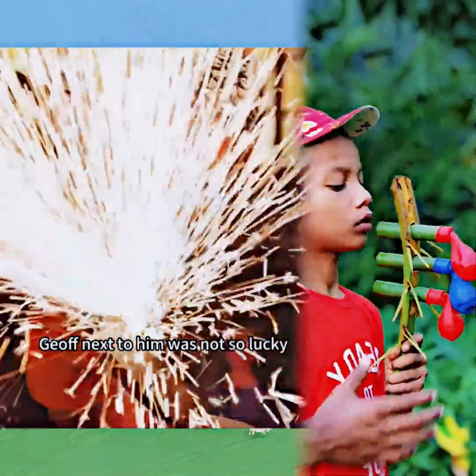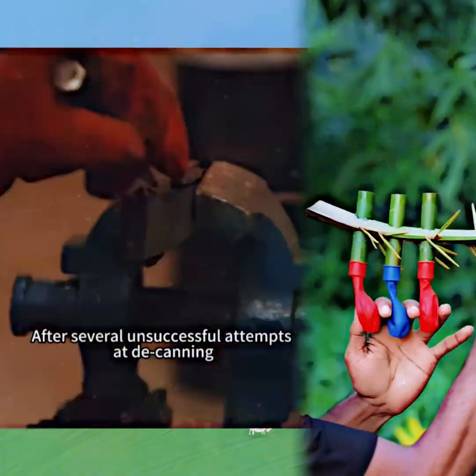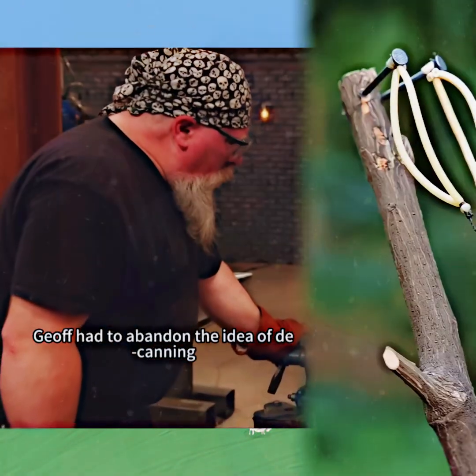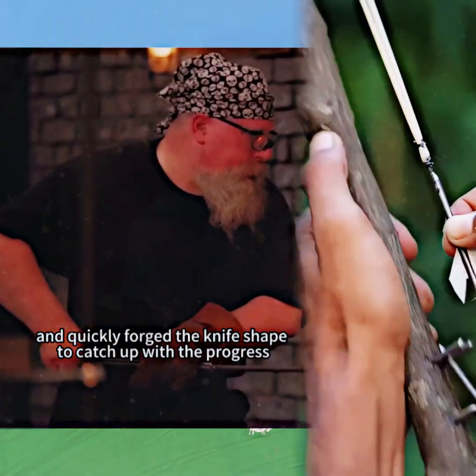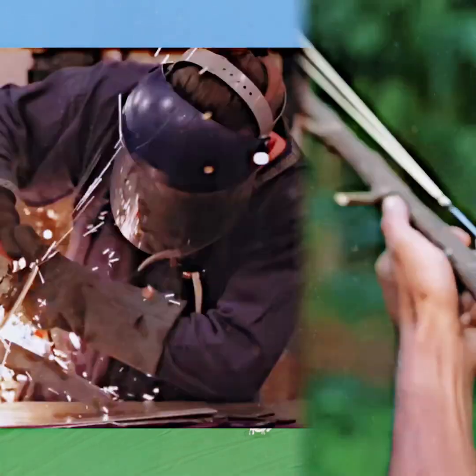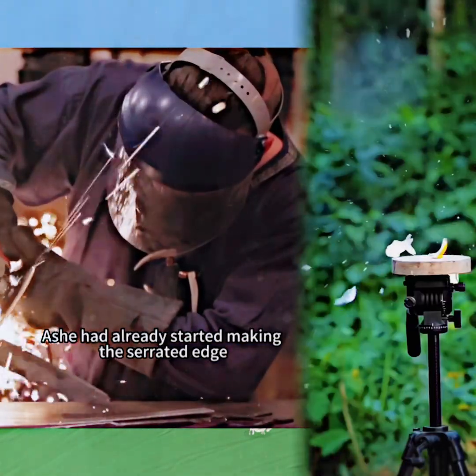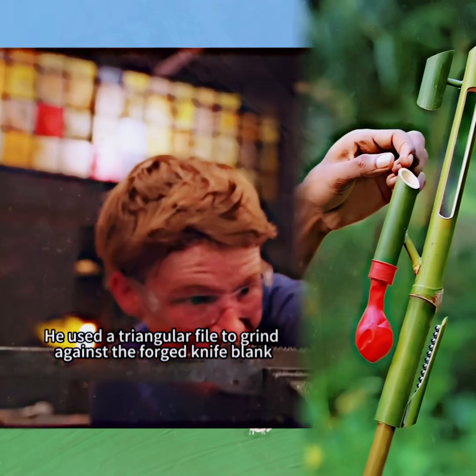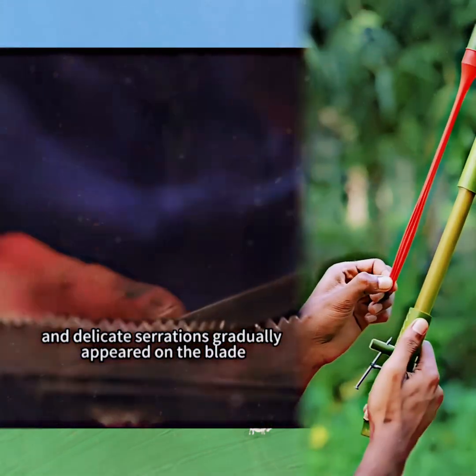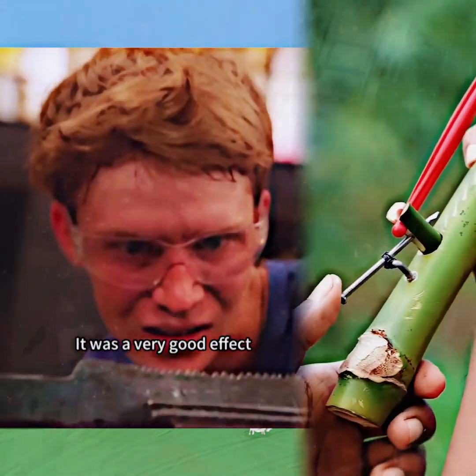Geoff next to him was not so lucky. After several unsuccessful attempts at decanning, Geoff had to abandon the idea of decanning and quickly forge the knife shape to catch up with the progress. At this time, Ashe had already started making the serrated edge. He used a triangular file to grind against the forged knife blank, and delicate serrations gradually appeared on the blade. It was a very good effect.